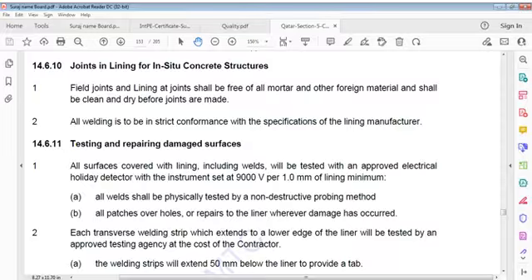So this is testing and repairing damaged surfaces. Once again, all surfaces covered with lining, including welds, shall be tested with an approved electrical holiday detector with instrument set to 9000 volts per 1 millimeter of lining minimum. All welds shall be physically tested by a non-destructive probing method. All patches over holes or repairs to liner wherever damage has occurred. Each transverse welding strip which extends to lower edge of liner shall be tested by an approved testing agency at cost of contractor. Welding strips shall extend 50 mm below liner to provide a tab.